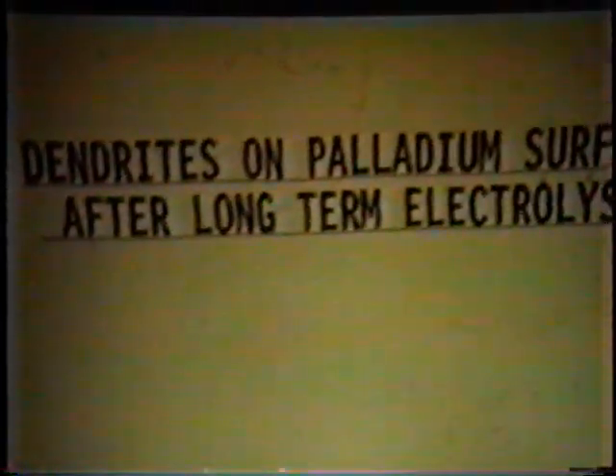This is Nomarski interference spectroscopy or interferometry and interference contrast microscopy to be precise. And you see, not only are there 2 obvious superdendrites, so to speak, which are about 2 microns high, but there are obviously loads and loads of little ones here, which may well have the types of radii of curvature, about 100 angstroms, which is needed for the acceleration type theory, which Kim, the University of Illinois, has been developing, partly, I think, on the basis of what we suggested way back there. And it's one of the mechanisms, one of the 4 mechanisms, I think, which we should consider in cold fusion at this time.